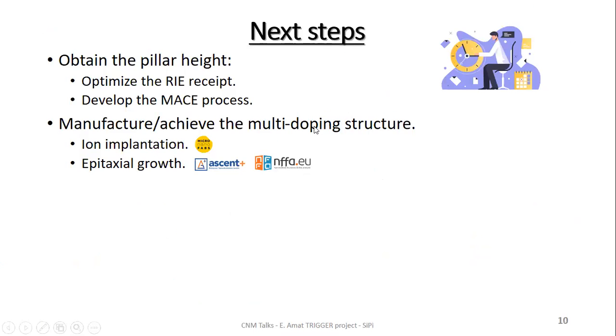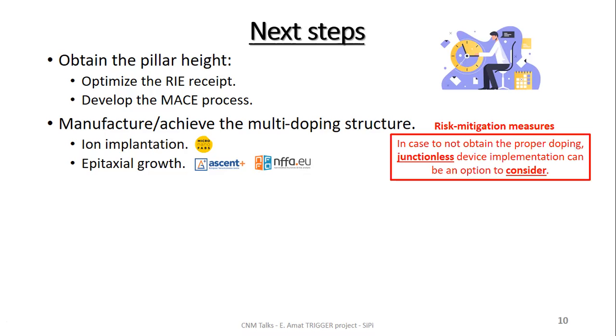The next steps are to obtain the pillar height, so we have to optimize RIE and MACE, and manufacture the multiple doping structure. As I mentioned before, ion implantation is made here in our clean room, and epitaxial growth by collaborating with ascent+ and nffa.eu partners. In case we do not obtain a correct multi-doping structure, one option is to implement the device in a junctionless option. Then we need only a highly doped silicon region.